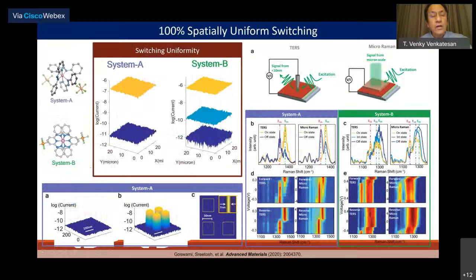What is also remarkable is when we combine these complementary oxide memristors, the interesting thing is that the switching is absolutely homogeneous. There is no filament formation. We are conducting images of the current profiles in the on state and the off state, and there's absolutely no inhomogeneity that one sees in this.